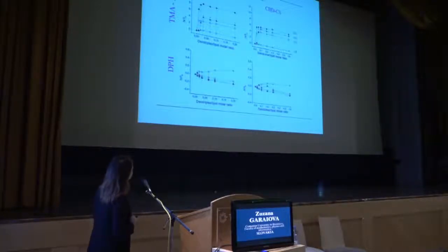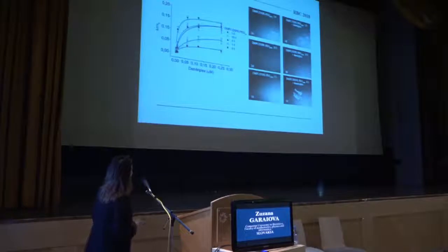And in the case of the hydrophobic core, these particles didn't interact with liposomes composed of PEG lipids. We observed a slight increase just for pure DMPC liposomes. And those results were also supported by measurements performed on lipid monolayers.